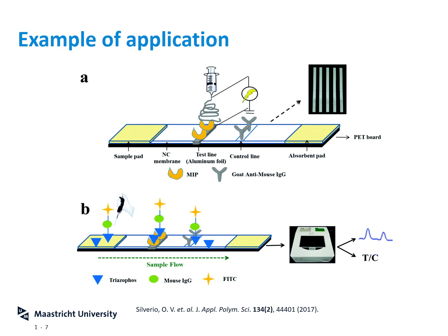So what happens is, if no target is present, then all that conjugated pesticide with the fluorescence label on it will bind to the first line, and you will get a very thick, very high concentration reading in the first test line for the MIP and the control line where you have antibodies immobilized too. So you will have two broad lines when no pesticide is present in your environmental sample.